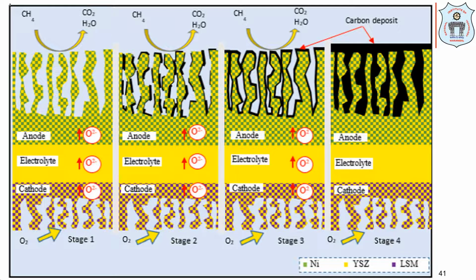That way we observe that in stage 3, the current density keeps decreasing with respect to time, because the more the carbon layer becomes less porous, there will be less diffusivity of the reactant through the pores to reach the surface, and so the reaction kinetics will be slowed down. So that's where we observe the lower current density. So this carbon deposition is porous and still allows the fuel gas to pass through and react at the anode surface, but at a lower rate, and hence lower performance is observed. Thus at this stage, the current, voltage or power density will be observed to decline as time progresses.